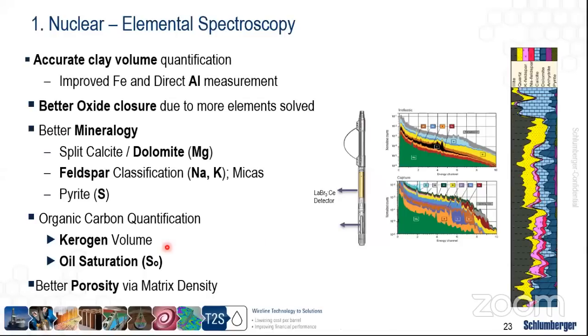Another element that we also measure is what we call carbon. So carbon is typically found in any carbon-rich material. Some of it can be organic carbon and some of it can be inorganic carbon. So organic carbon is typically anything like oil, bitumen, kerogen, gas, light oil. And inorganic carbon typically comes from the chemical composition of different lithologies, such as calcium carbonate, which is limestone, calcium magnesium carbonate, which is dolomite, siderite, etc.